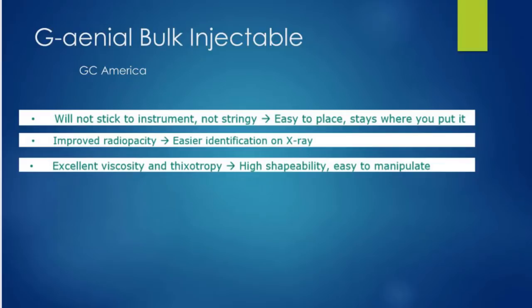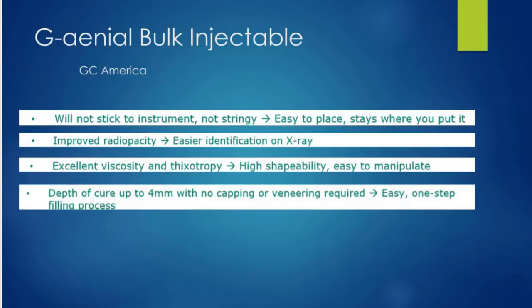It has a depth of cure of 4 millimeters, and you can confidently do that a millimeter away from the tooth up to about 5 millimeters. I'd be very, very leery of going beyond that 1 millimeter away from the tooth. So if your proximal box is deeper than 4 millimeters, I wouldn't do it. I'd also be very, very careful about what many manufacturers say with 6 and 7 millimeter depth of cure, because that also doesn't account for things like angulation, undercut, and many other issues that lead to poor photopolymerization.